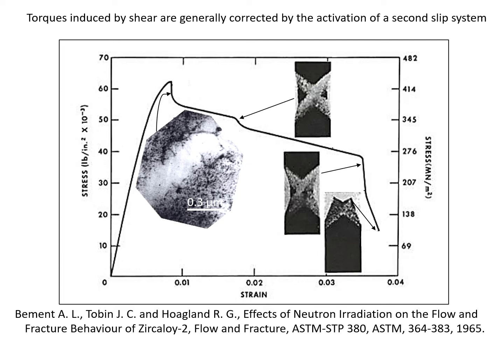So now it is easier to deform because this is essentially annealed material. And that shows up as a load drop. So it's less stress to create strain. So we drop the stress at this point. It's not true stress, of course, it's an engineering stress, but it would still manifest itself even on a true stress strain curve because you're essentially softening the material.